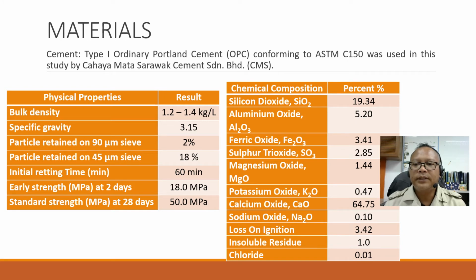For the chemical composition, the highest percentage is calcium oxide, about 64.75%, then silicon dioxide 19.34%, and the others of the chemical composition are less than 5%, which are aluminum oxide, ferric oxide about 3.41%, sulfur trioxide 2.85%, magnesium oxide 1.44%, potassium oxide 0.47%, sodium oxide 0.1%, and loss on ignition 3.4%, insoluble residue 1%.